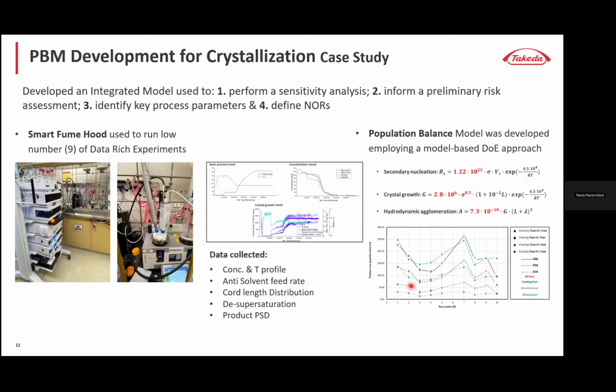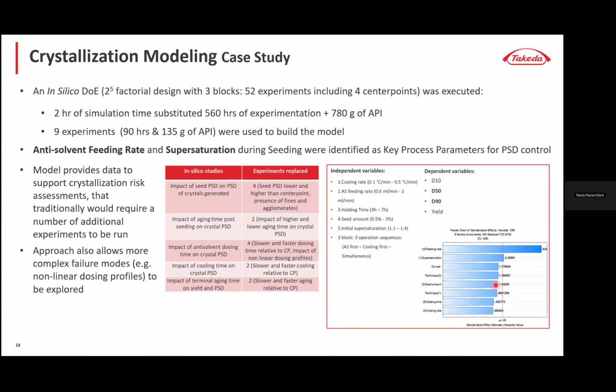Then, as we went through the workflow that I showed before, the model-based design of experiments, we gradually added more experiments. These are all very data-rich experiments where we measure the concentration. We looked at a lot of different orthogonal methods for measuring concentration and size, and how they change during the experiment. Using these experiments, we managed to build a population balance model for the crystallization, as you can see.